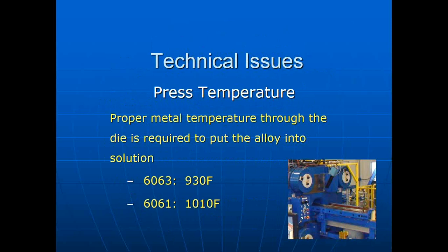The intent with the structural alloys is to return all magnesium and silicon into solution as the metal flows over the bearing surfaces in the press, and specifically in the die inside the press. You have tremendous heat from deformation as you're going through the bearing surfaces, and that normally will return the magnesium and silicon back into solution. We have minimum temperatures to achieve that. They're different for each alloy. 6061, a very common structural alloy, is 1010 Fahrenheit.